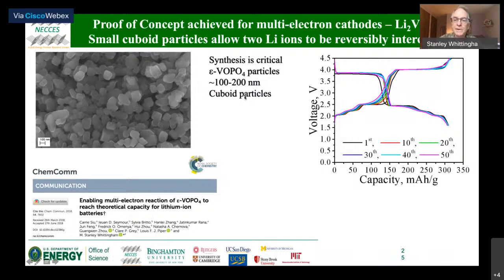And using these materials, we then get this electrochemical behavior. You can see vanadium 5 to vanadium 4 at just under 4 volts, then vanadium 4 to vanadium 3 at between about 2¼ volts to just under 2 volts. And you'll see these bumps here. This is lithium ordering in the structure. And this has no effect on electrochemical behavior, except that when you're actually moving lithium ions, this becomes single phase, so it's very high rate.